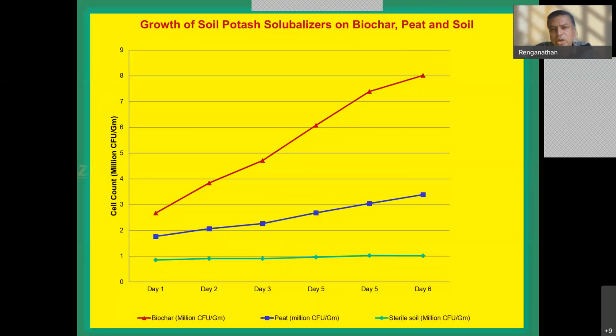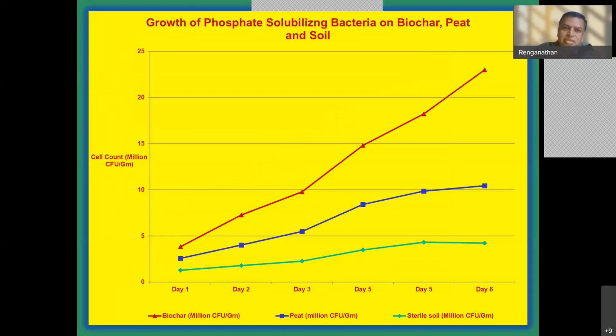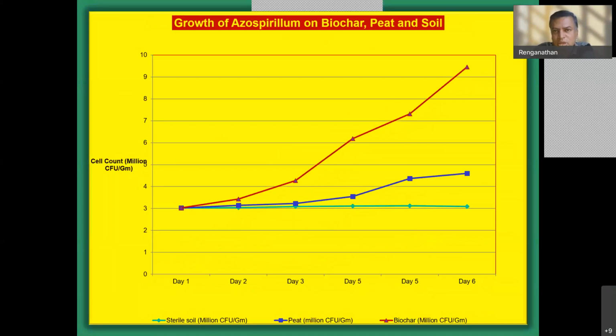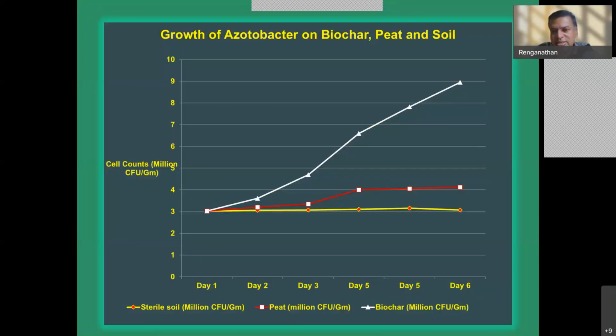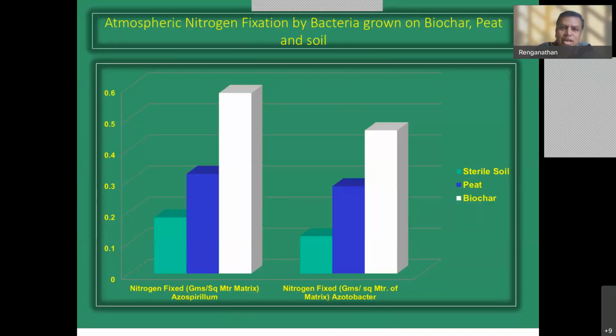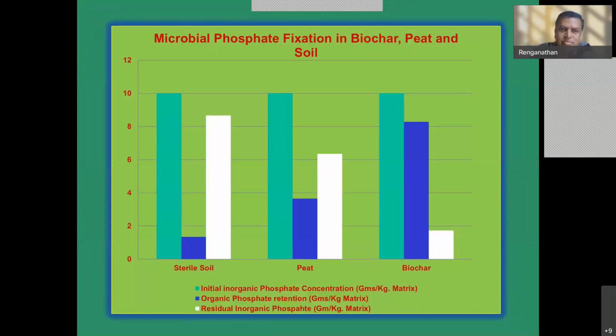This biochar also supports potash solubilizers, and you can see from the experimental data that where you have biochar, the potash solubilizers are higher. The same case happens with phosphate solubilizing bacteria. The same is the case with azospirillum. The same is the case with azotobacter. These are nitrogen fixing bacteria. So the atmospheric nitrogen fixation bacteria grown on biochar peat soils have been represented here. If you see, biochar-amended soils have the highest amount of nitrogen fixing bacteria. And the same is the case with phosphate fixing bacteria.